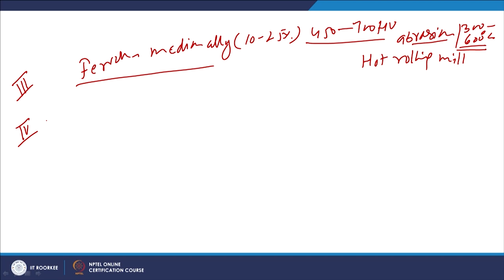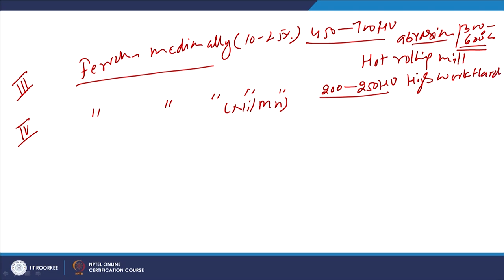And then we have another category, category 4, which is also a ferrous medium alloyed steel having 10 to 25% alloying concentration, but these are of very low hardness, like 200 to 250 HV. Basically alloying of nickel, manganese kind of elements are used. So initially their hardness is low, but these offer very good work hardening capability. Because of this, these suit impact, adhesive and abrasive wear conditions very well. So these are used where impact coupled with abrasion and adhesion is involved.